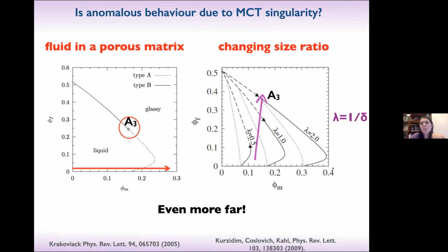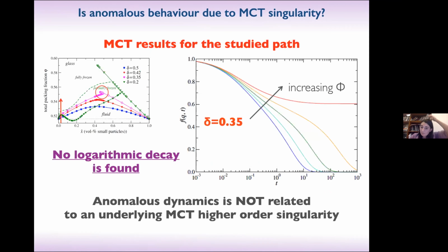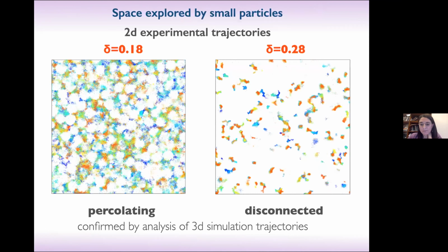We find a logarithmic dependence that is a different object. But just to be sure, Thomas Voigtmann calculated the density correlators along this path, and actually confirmed that the theory would not predict the onset of logarithmic relaxation.